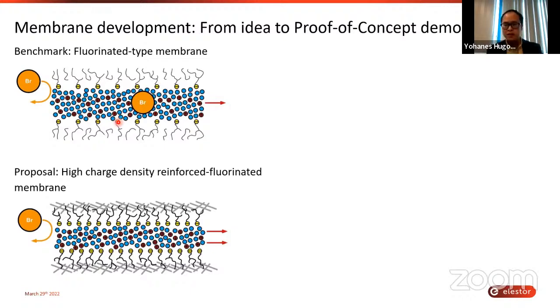where it's basically a composite membrane, a mix between the PFSA and a non-conductive polymer. The non-conductive polymer can constrain the PFSA mechanically. So when it comes in touch with water, it will not swell as much as a normal PFSA. Therefore, we can still have a very high conductivity while blocking the bromine species from going to the other side.